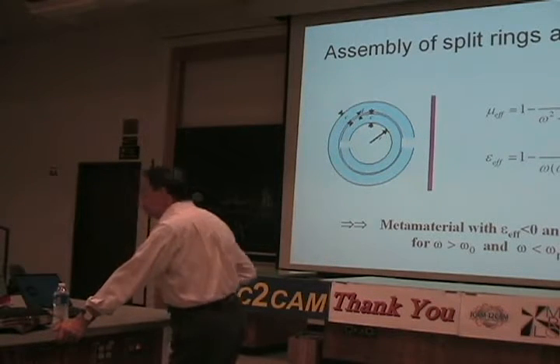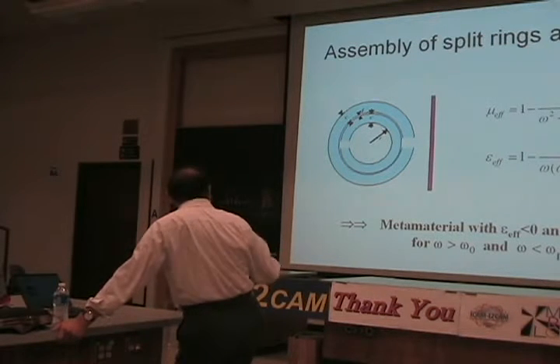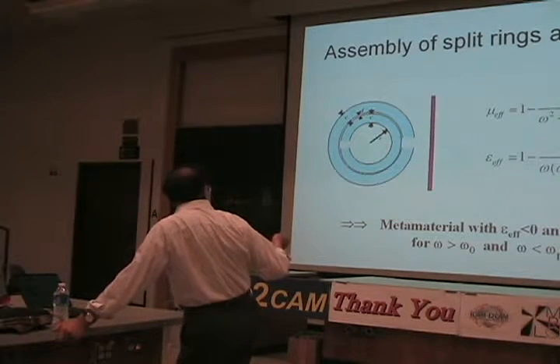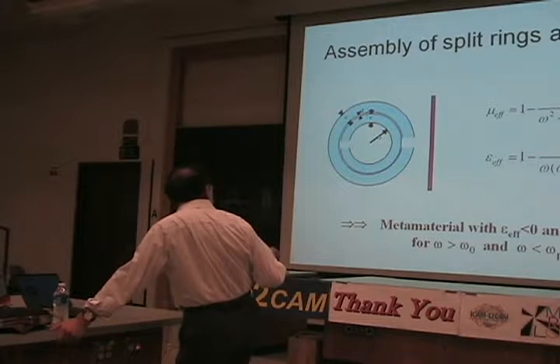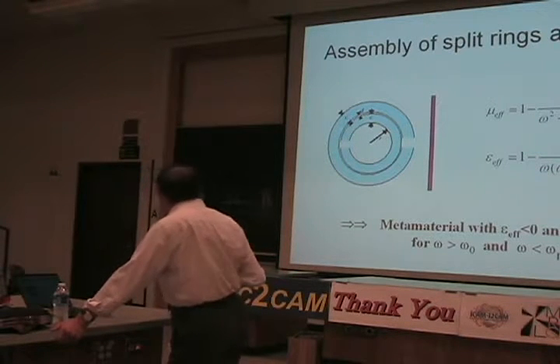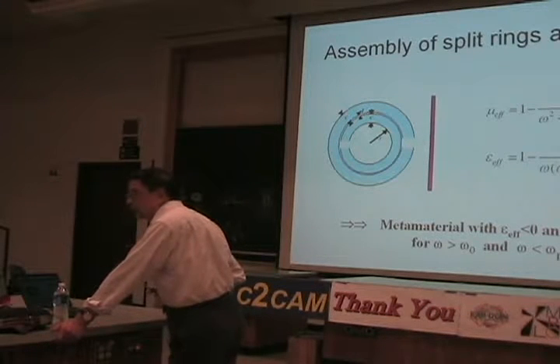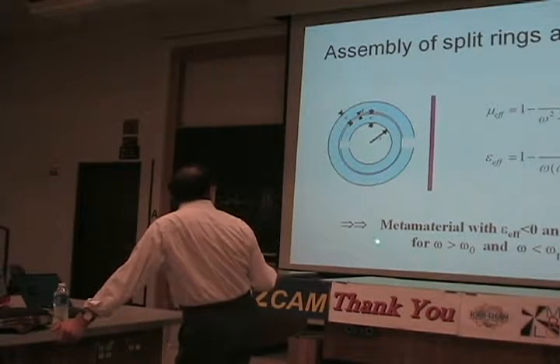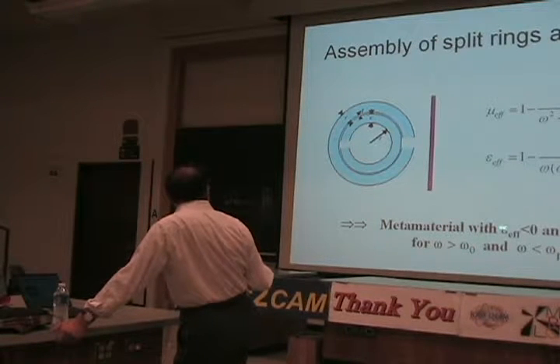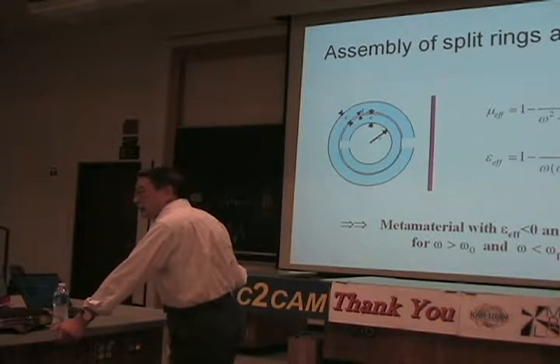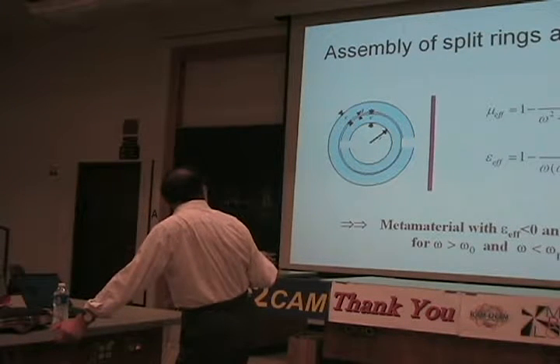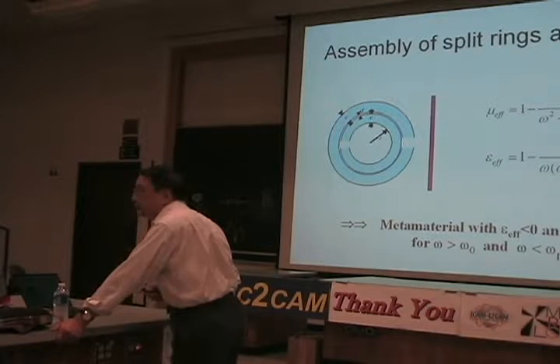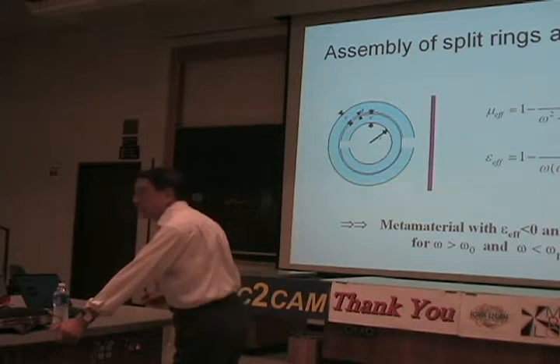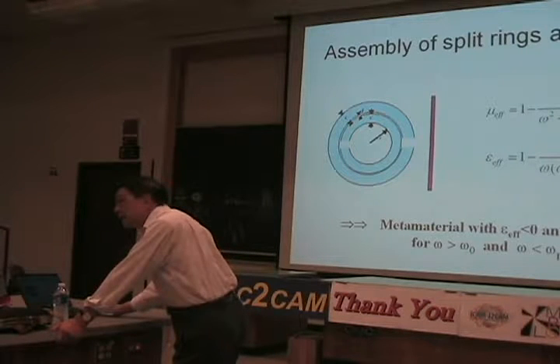plasma resonance. The plasma response is, omega p is the plasma resonance frequency, and we have this usual expression. And you can see that if omega is smaller than omega p, epsilon will become less than 0, or even less than -1. And you can see in that case, the metamaterial will have both negative dielectric constant and negative magnetic permeability. And that is what we are interested in for the negative refractive index materials.